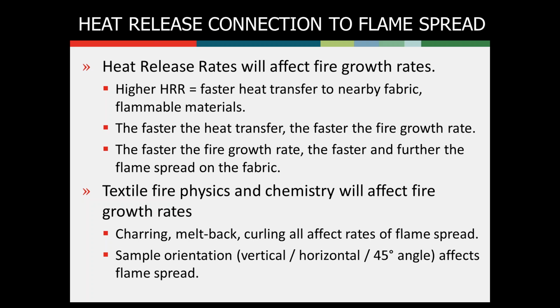Does the fabric char? Does it melt back? Does it curl away? Does it fall apart? And that's all going to affect your rate of flame spread. It's not uncommon for thermoplastic fabrics to melt back, and then the flame stops propagating if the flame is held constant. But you can imagine if that flame were to chase along the fabric, it's eventually just going to burn it to completion.